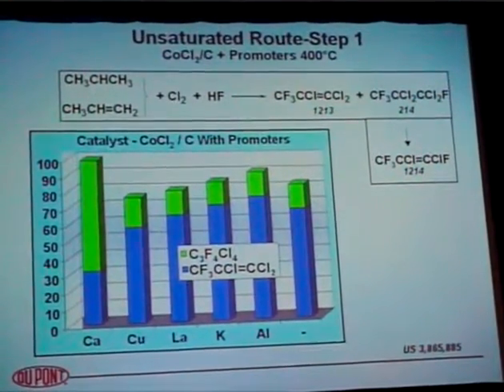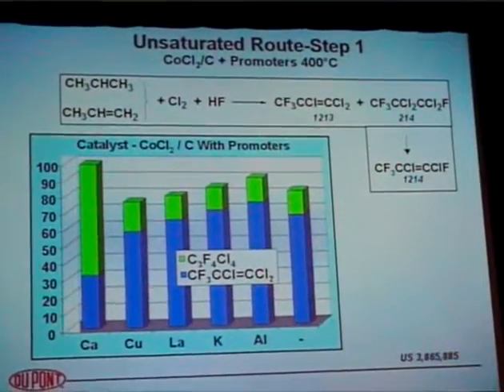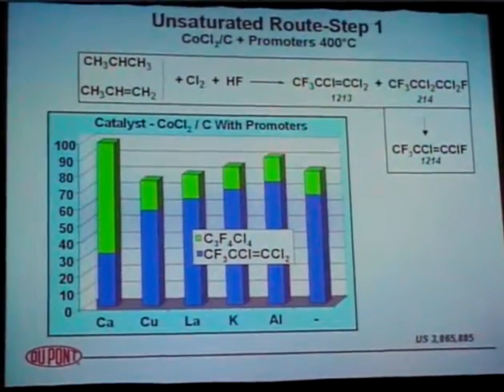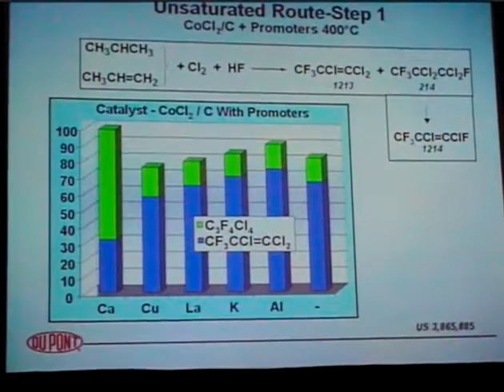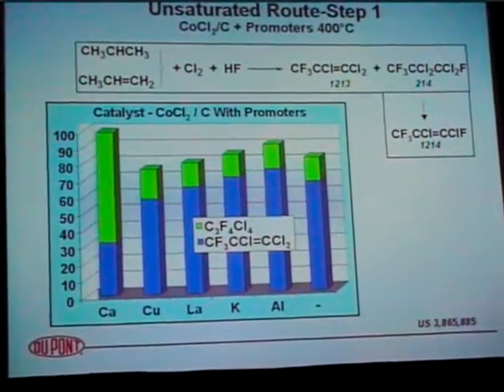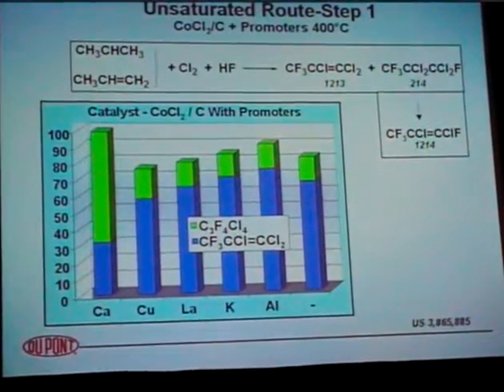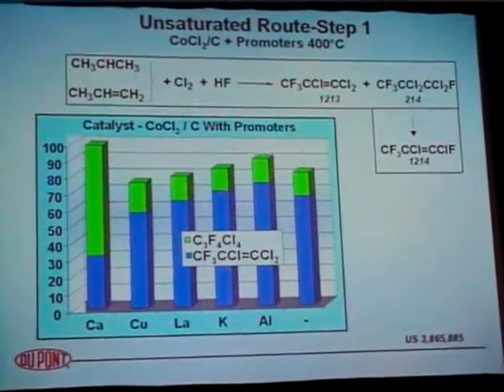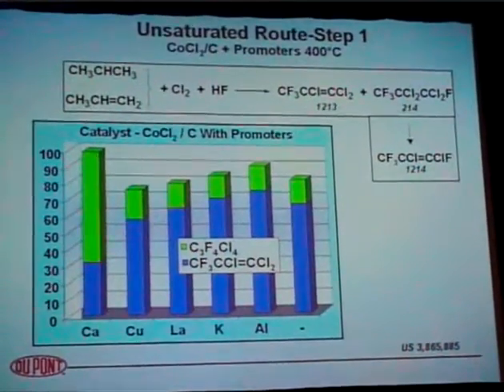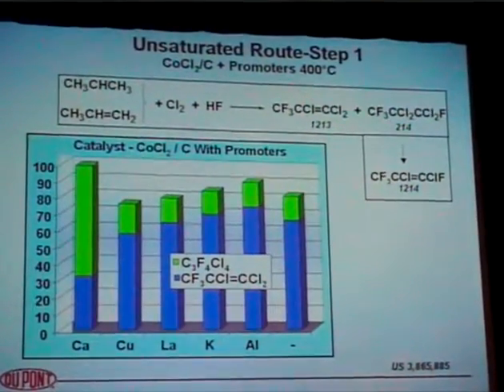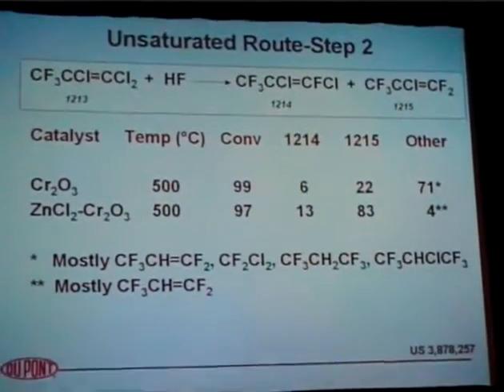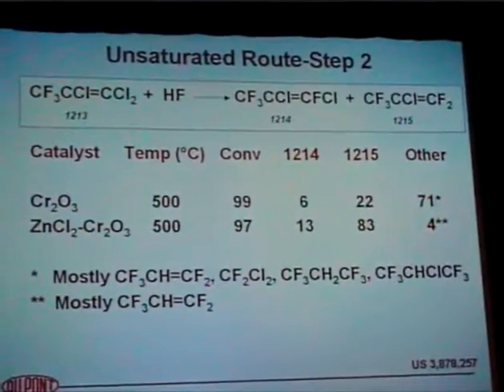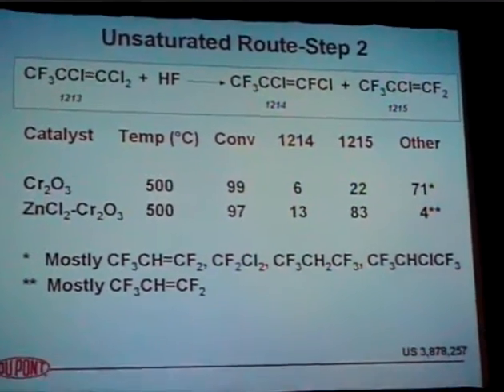If you don't use the cobalt chloride, the various materials are shown in the chart on the left-hand side, a little bit of calcium in there, you can get up to around 95% overall yield to the combined products of the 12-13 and basically 12-14, the tri- and tetrafluoropropylene. So those are the materials now that we'll take on to the next step. And here we are again, another remarkable reaction, taking trichloropropylene, reacting it with HF, not adding the HF, but exchanging the HF to make those two olefinic intermediates.